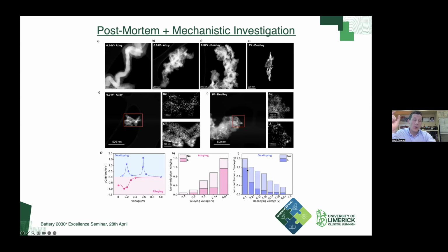The dealloying is even more interesting in that you're starting out from your lithium-rich system that we finished with here. What happens initially is that while your overall ions are obviously decreasing as you're dealloying, your sodium ion contributions are actually slightly increasing. So you see the relative amount of sodium is increasing. For us, that was a really difficult mechanism that we needed to try and explain.